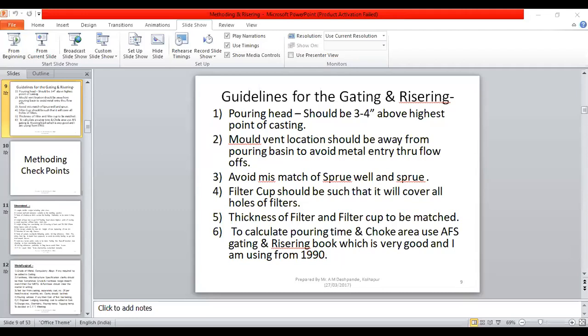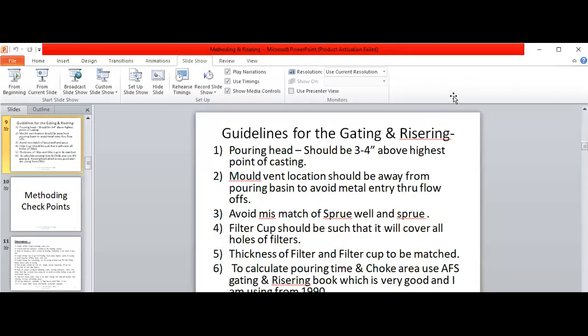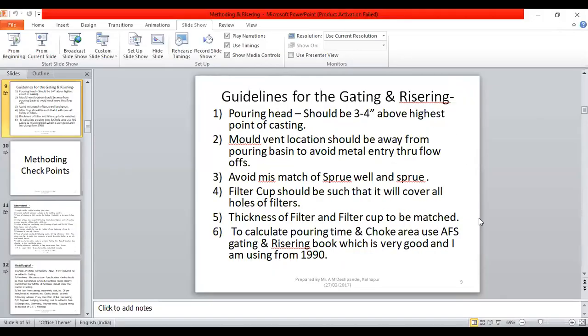Mold vent location should be away from the pouring basin to avoid metal entry through flow offs. Avoid mismatch of sprue, well and sprue.